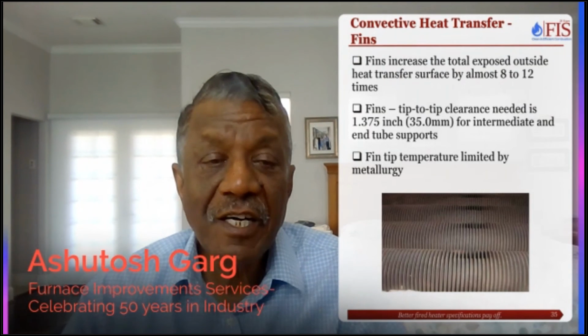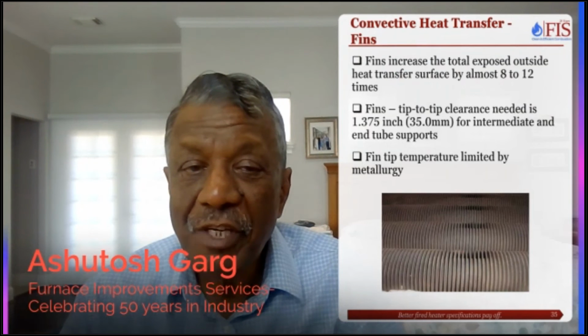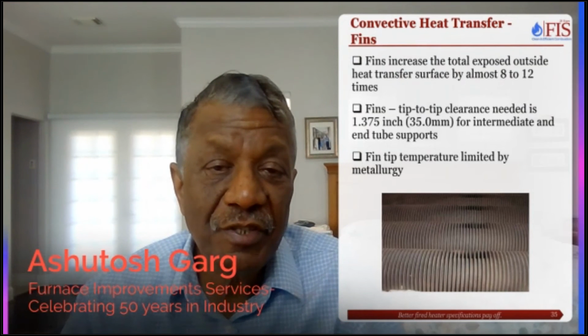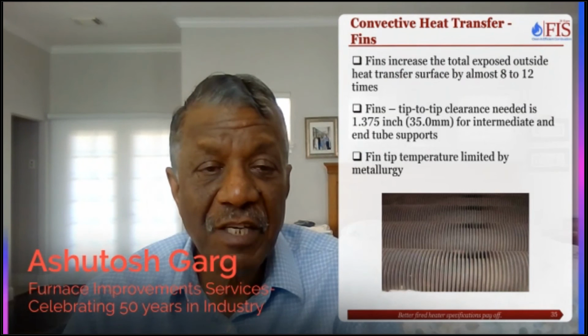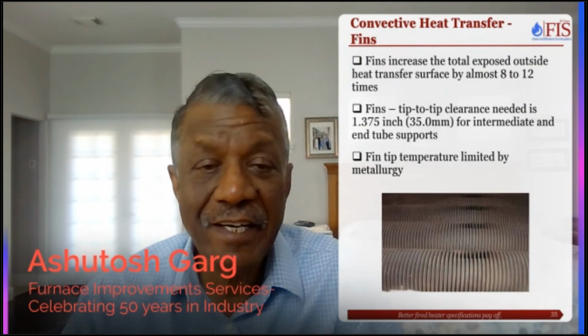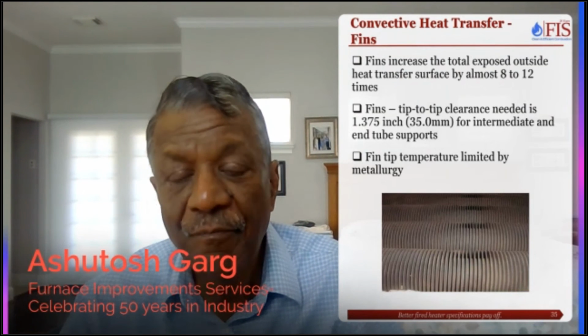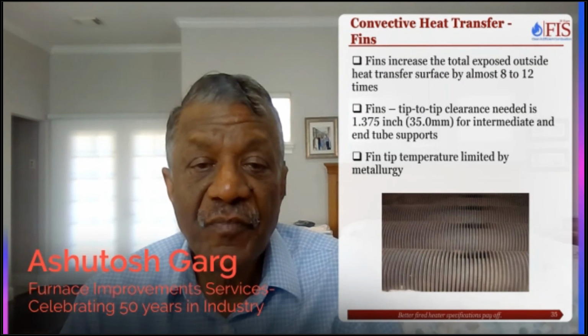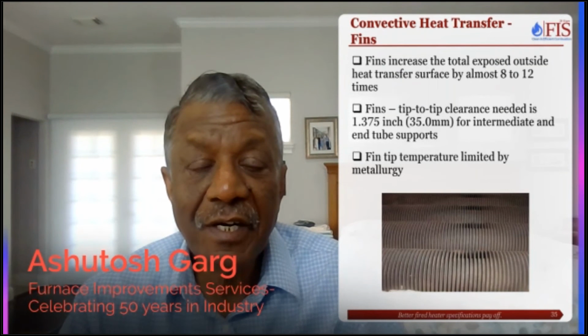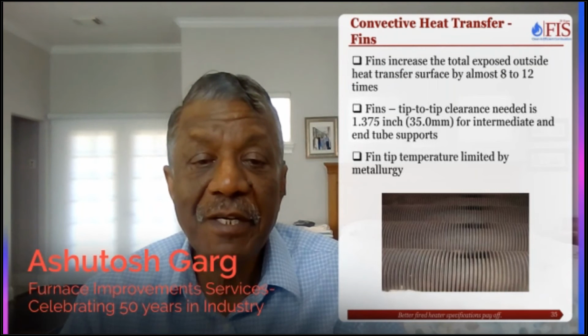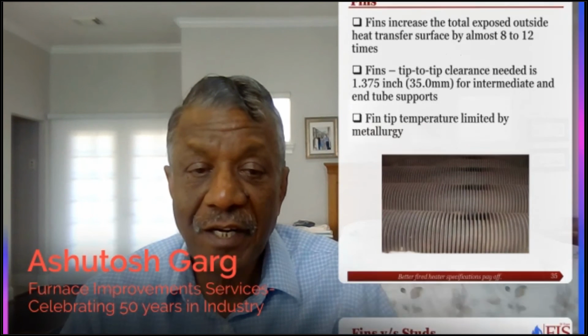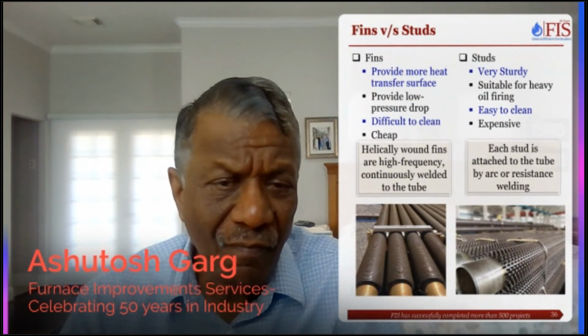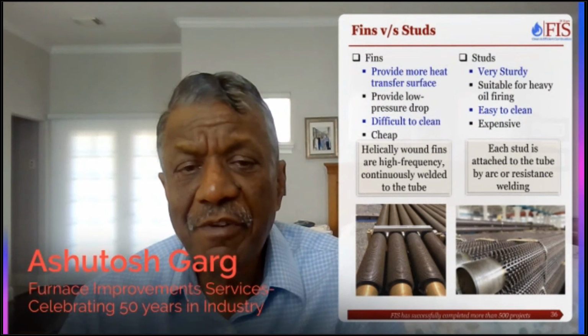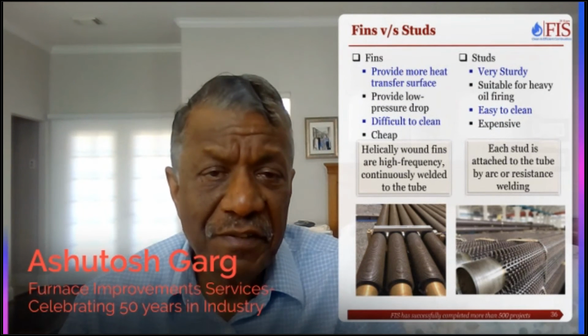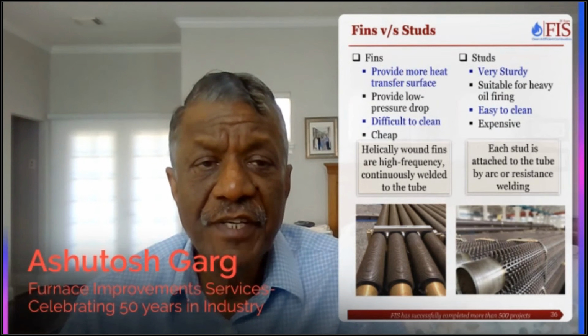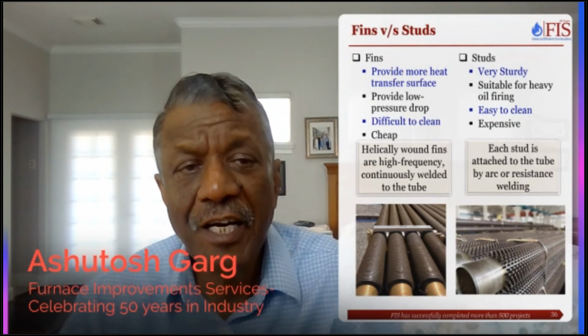We do need a tip-to-tip clearance, fin tip-to-tip clearance, which is about 1.375 inch or 35 millimeter for intermediate and end tube supports, just to provide the ligament thickness. And fin tip temperatures are limited by the metallurgy. Tip temperature is the hottest point in the whole heat transfer. There are different types of extended surfaces. Fins are the new ones. Studs have been there for a long time.